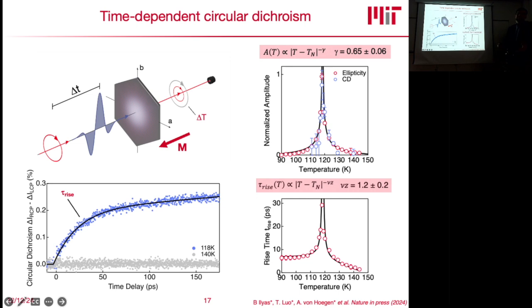So it's very much compatible with a second order phase transition, where close to the phase transition you have softening of modes, and therefore the critical slowing down, because your energy differences between the excited state and the initial state are so small, so the driving forces are very, very weak. And so we find this divergence in the rise time.